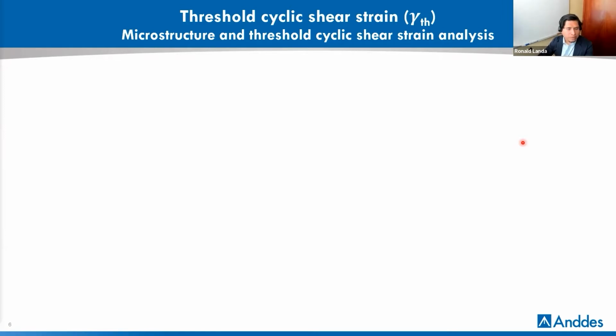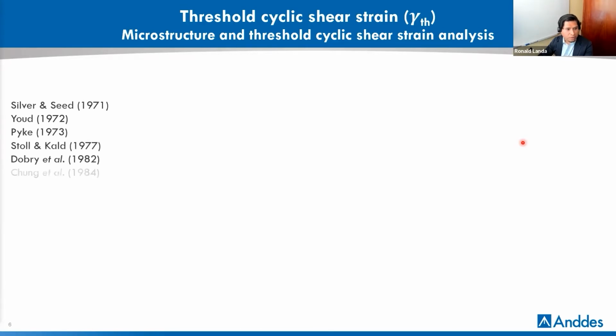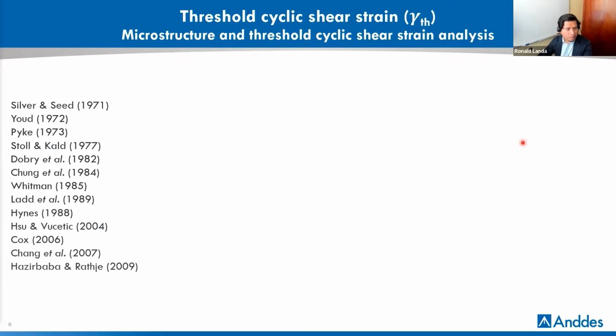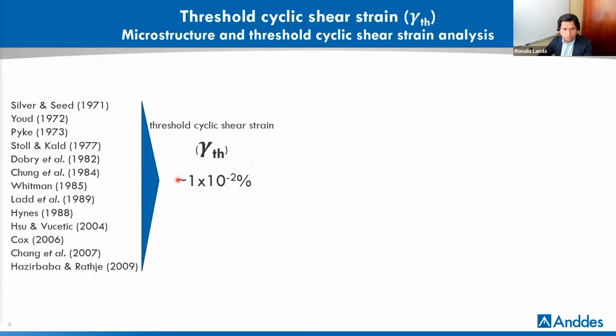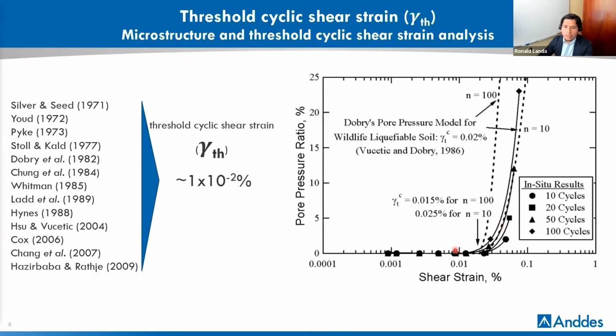So just to defend this point, Silver and Seed 1971, Youd, Pyke, Stoll and Kald, Dobry, Chung et al., Whitman, Ladd et al., Hynes, Hsu and Vucetic, Cox, Chang et al., Hazirbaba and Rathje, they all concluded that the threshold cyclic shear strain exists, which is approximately 10 to the minus 2 as a percentage, and is an aspect that links the onset of earthquake-induced pressure buildup. It's a backbone value or fact from the cyclic strain theory proposed by Dobry in 1982 that we can include in this standard approach.